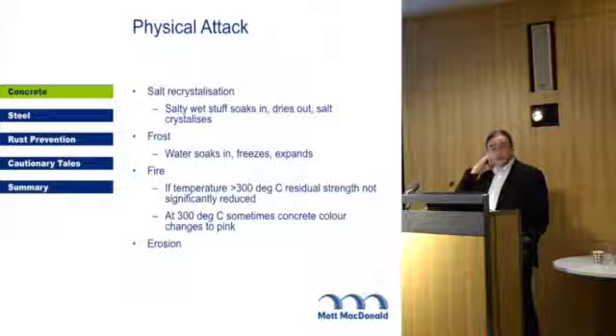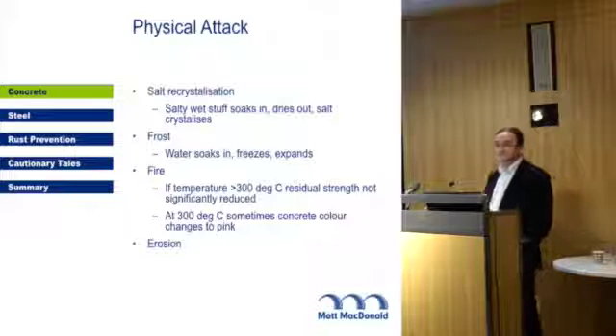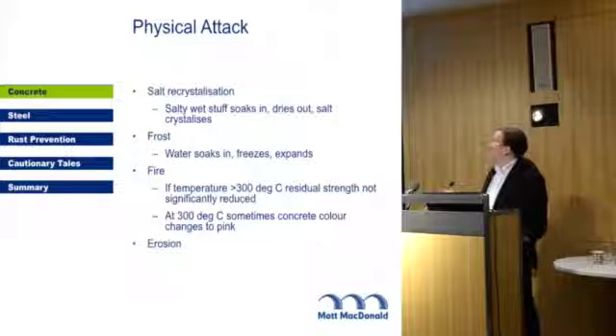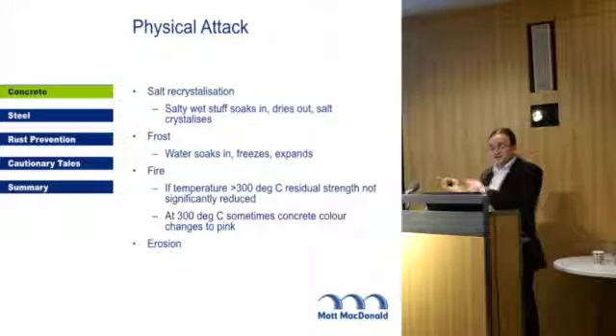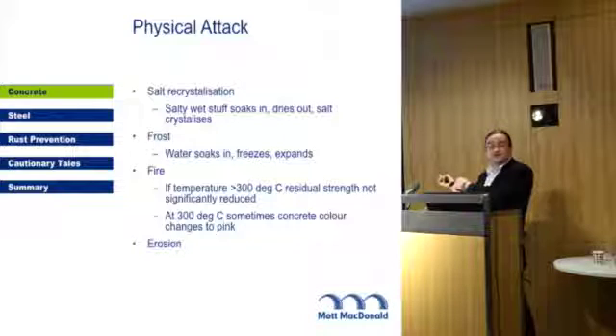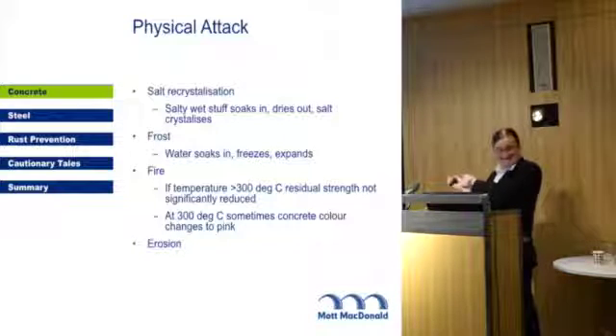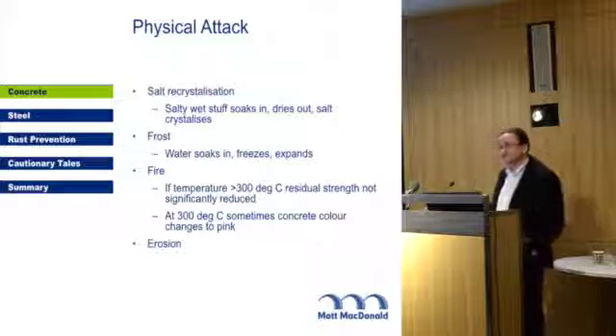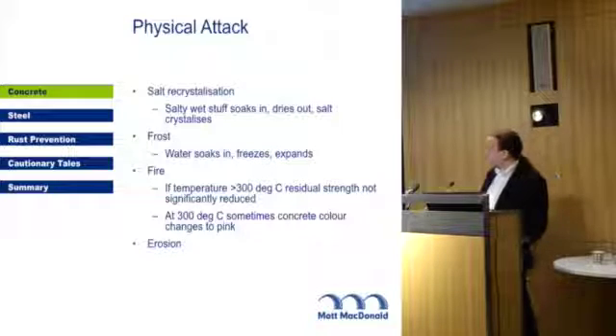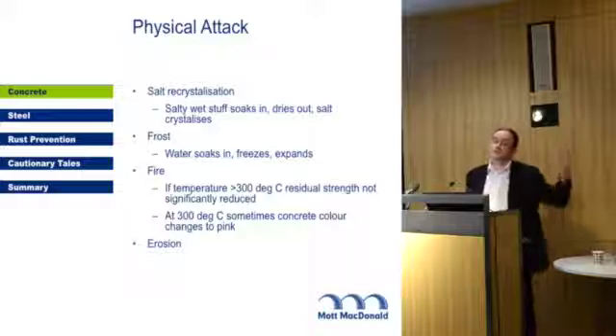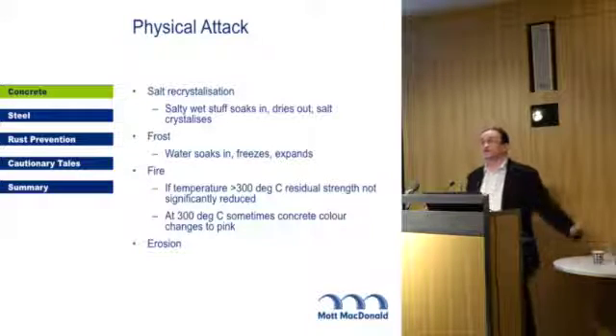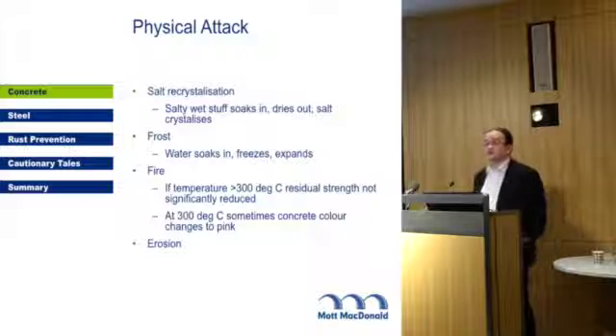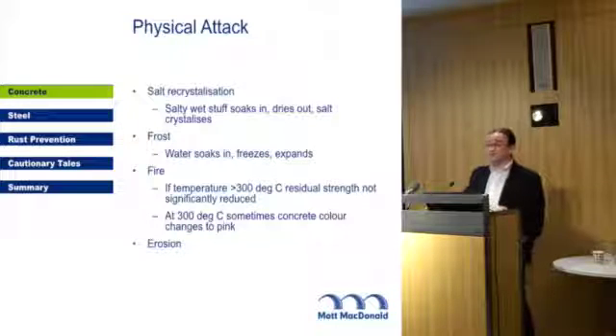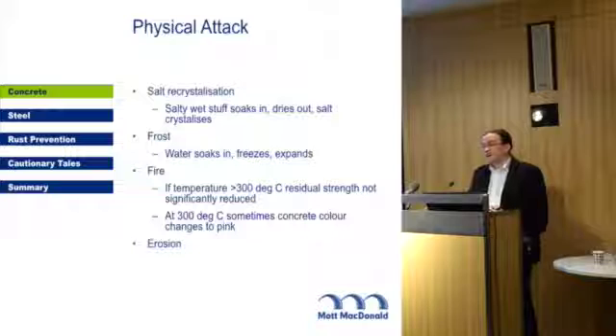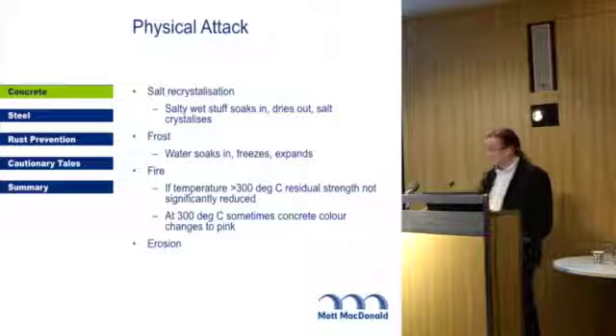Occasionally people set fire to things under concrete bridges for some reason best known to themselves. They burn cars out and things burst into flames in the Channel Tunnel. Generally for concrete, I know it says if the temperature is greater than 300 degrees C, the strength's not affected. Actually, that should be less than 300 degrees C. At 300 degrees C, sometimes some concrete changes to pink. Doesn't always happen, so if you turn up at a fire damaged structure, knock a lump off, find it hasn't gone pink, it doesn't mean it's not got that hot. To be honest, if you get asked to turn up at a concrete structure that's had fire damage, it's had fire damage because that's why somebody's paying you to go.